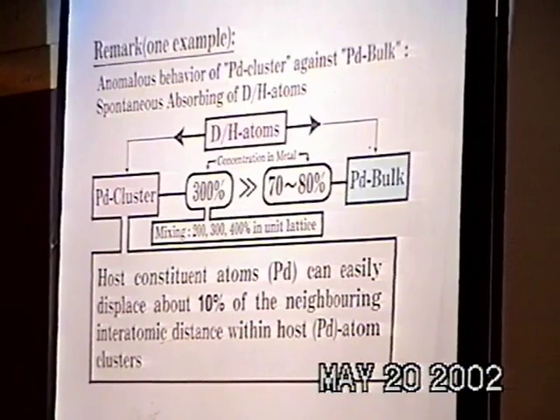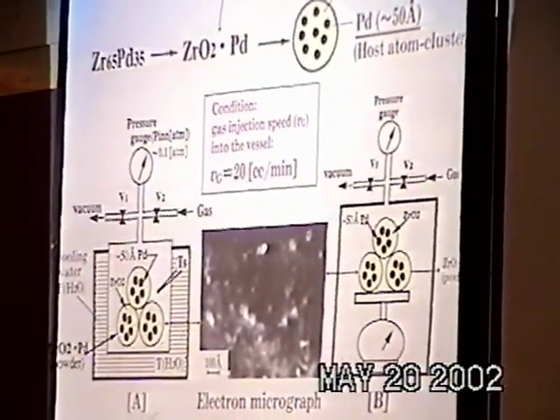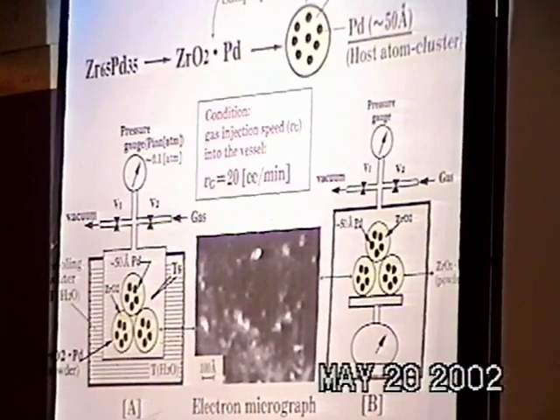This remarkable difference between atom clusters and bulk metal decides whether nuclear reaction succeeds or not in atom clusters. This is just a very important situation, but the only trouble of atom clusters is easily sintering during experiments. Next, please. In order to avoid this trouble, we have developed special type palladium clusters, which are embedded within ZrO2 powders, as shown in this slide.